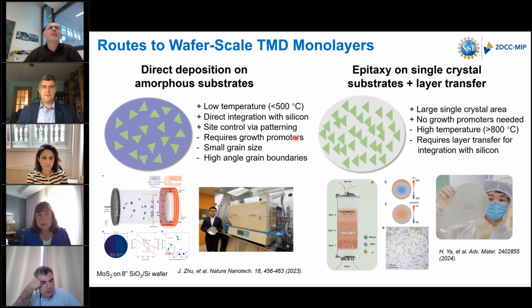But there are some downsides. This process often requires the addition of growth promoters like sodium chloride, which can add impurities into the material. And also the lower temperatures can result in small grain sizes and high angle grain boundaries in films that are coalesced. But nevertheless, there have been some really impressive demonstrations, for example deposition of molybdenum disulfide on 8-inch diameter oxidized silicon. The other approach then is to do epitaxial growth on single crystal substrates. So this would be a substrate like sapphire.